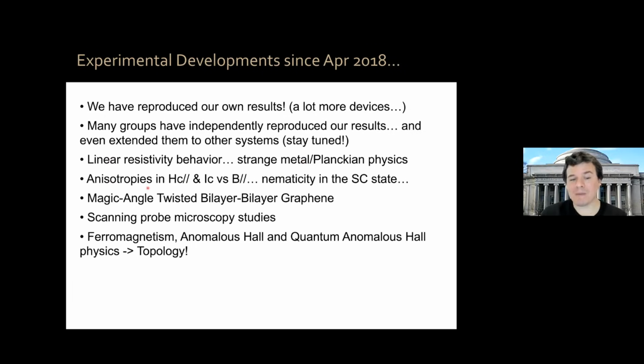We have many other systems now that exhibit correlations when you twist them. The second one after magic angle graphene was magic angle twisted double bilayer graphene, 4 layers, one pair with 0 degree angle, one pair with 0 degree angle, and now these pairs twisted by 1.1 degrees. There have been many scanning probe microscopy studies, and we have been discovering new and new phases in the system, okay? In particular, ferromagnetism, and we have measured also anomalous Hall and quantum anomalous Hall physics, which indicates that the system has interesting topological physics in it, okay?